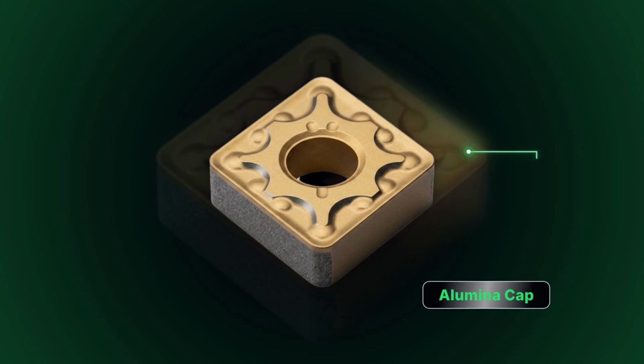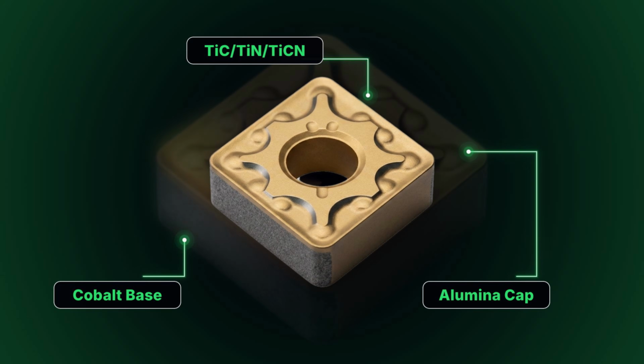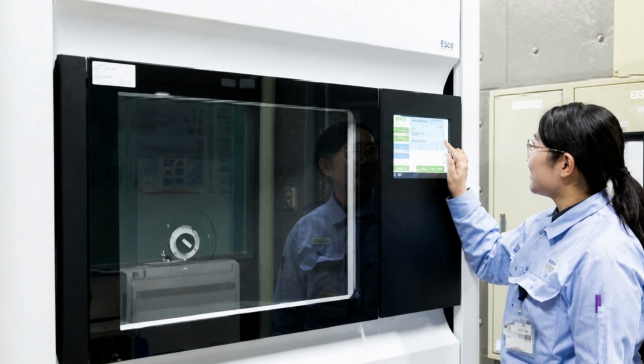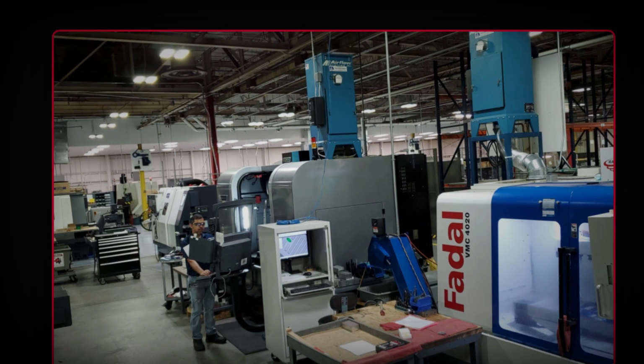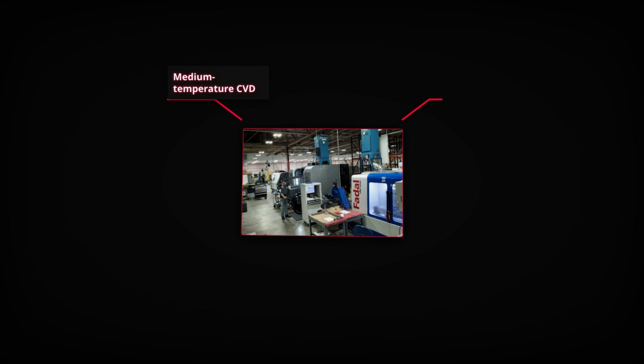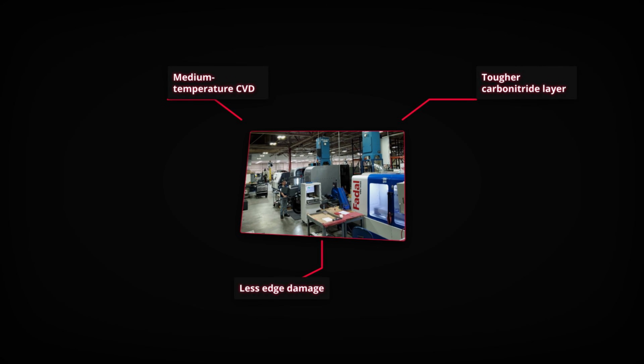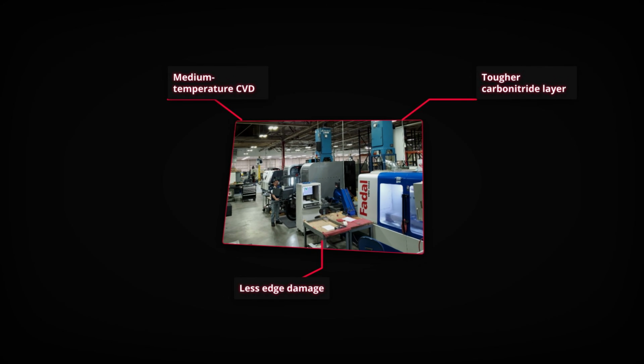CVD reactors running near 1,000 degrees Celsius learned to stack chemistries: titanium carbide, titanium nitride, titanium carbonitride, capped with aluminum oxide, a ceramic thermal barrier grown right onto the tool, and later, medium-temperature CVD processes deposited tougher, smoother carbonitride layers, with less damage to the edge.